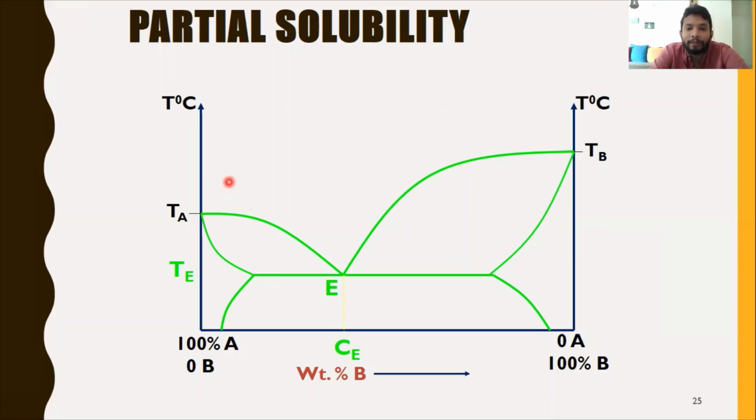So here alpha occurs, and also in this region we know B is high. B is 100%. If you take this dot here, it is 99% B and 1% A. And if you collect A and B here, it does not become A and B like earlier, it becomes beta. Here it becomes beta. So they dissolve with each other very well. Alright. In the middle, what happens is, alpha and beta will form, but this alpha and beta are not much compatible.